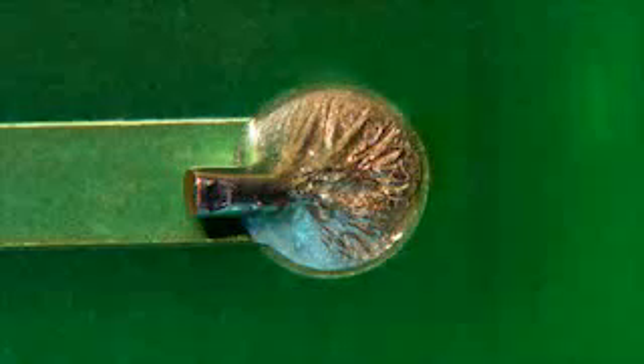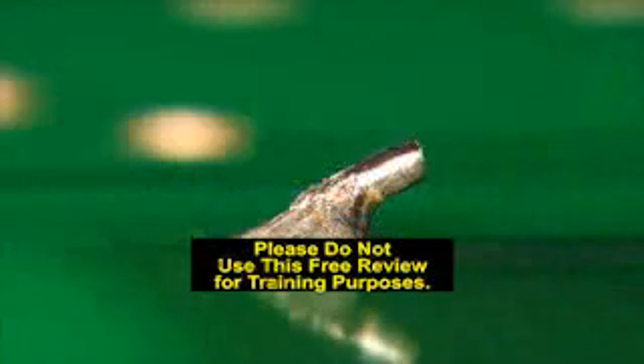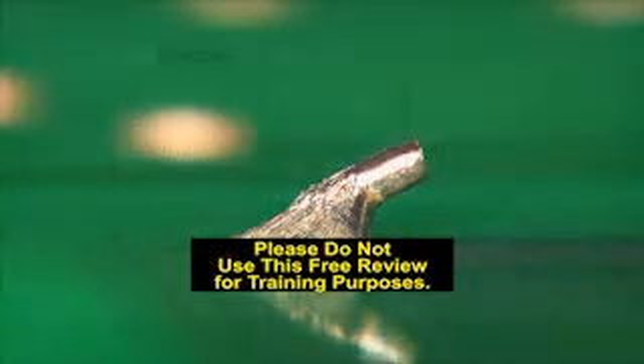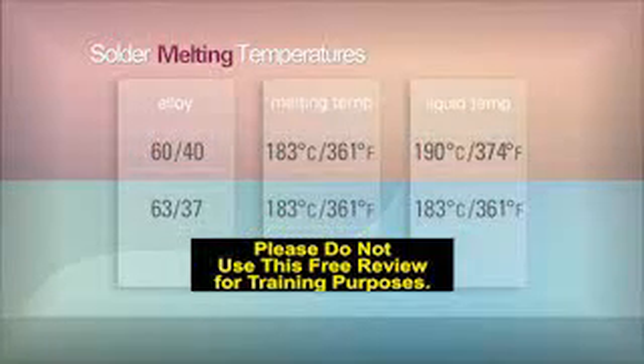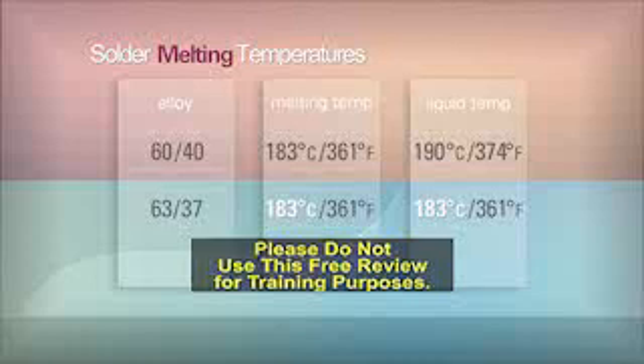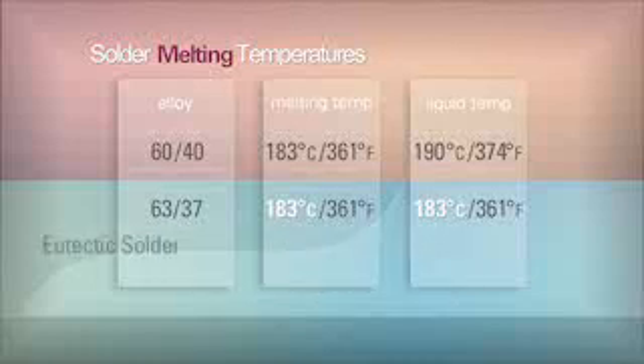60-40 solder begins to melt at 183 degrees C, but does not become fully liquidus until it reaches 190 degrees C or 374 degrees F. This 7 degrees C difference is called the plastic phase and is extremely critical during the heating and cooling of the solder joint. Movement during the plastic phase can cause a disturbed or fractured joint. Disturbed or fractured joints may be unreliable. 63-37 solder, however, has no plastic phase. It melts and cools completely at 183 degrees C and is known as eutectic solder. Because of this, and because it also quickly solidifies, 63-37 solder is commonly used.